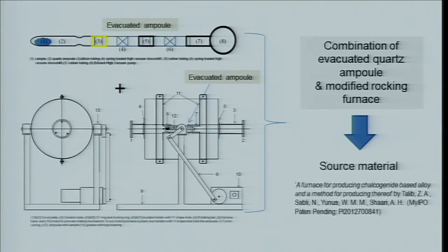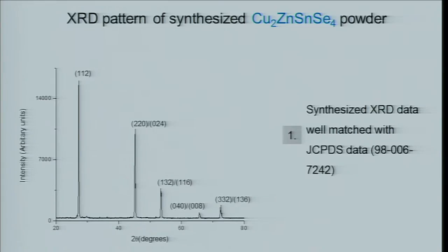And once we have that, we then put it in what we call a rocking oven. And this system was patented about 2-3 years ago. Once we think that it has gone through the full reaction, we stop it and then quench it either in air or in water or in liquid nitrogen. Again, we get wonderful results using this type of approach. And a lot of the students later on have used this approach to produce their compounds. And it worked almost every time.